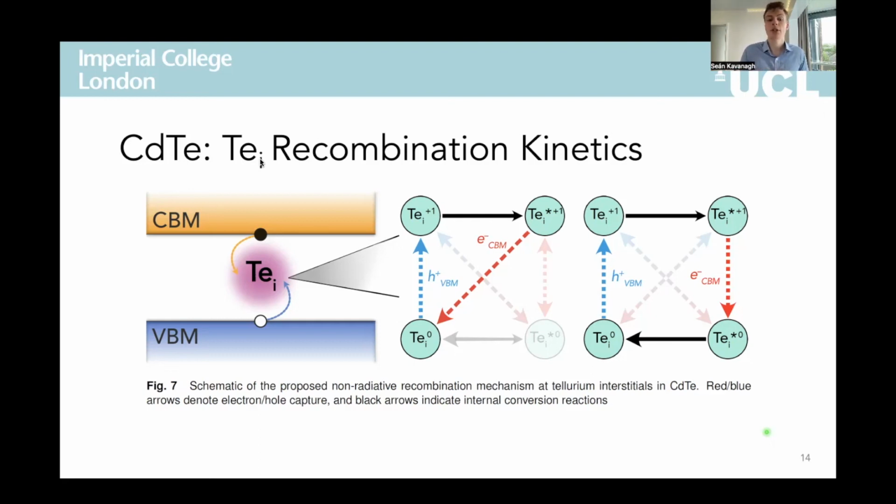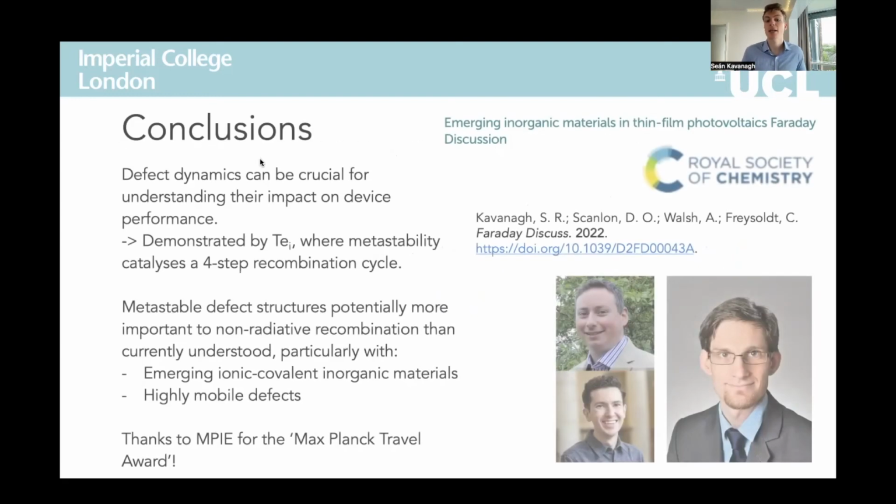While the earlier studies I showed looked at similar behavior involving capture into a metastable structure before relaxing and then capturing back to the initial state, this process actually involves thermal excitation to a metastable structure before capture, and has not been previously reported to the best of our knowledge. The main conclusions from this work are that the dynamic behavior of point defects can be crucial for understanding their impact on device performance, demonstrated here with a case study on tellurium interstitials in cadmium telluride.